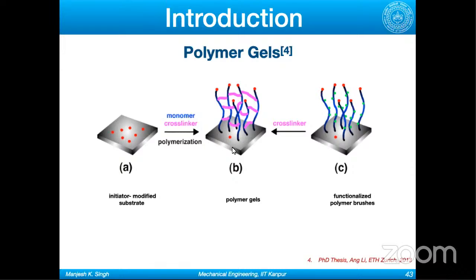There are two methods to create these cross-linked polymer brushes, also known as polymer gels. One is the initiator modified substrate, which we also call the in situ method, where while you are growing the polymer chains out of the initiator, you cross-link them. The other one is post-processing, or ex situ, where you first grow the polymer chains. You have functionalized monomers or ends in the chain, which after you grow the polymer brushes, you get to react to form the polymer gels. In the experiment I am showing you today, the polymer gels were prepared using the second method, the ex situ method. But I would like to tell you that I am not a chemist, so I didn't do this part.